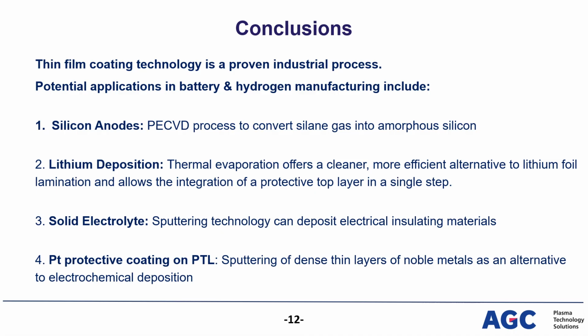First case study was for the use of the PECVD source to convert silane gas into amorphous silicon to produce 100% silicon anode. The second example was the thermal evaporation of lithium for lithium metal anode production as an alternative for lithium foil lamination. The third example was about the sputtering of solid electrolyte, particularly challenging because an electrolyte is an insulating material. And the fourth and last example was dealing with the sputtering of a platinum protective anti-corrosion layer on the PTL for a PEM electrolyzer.